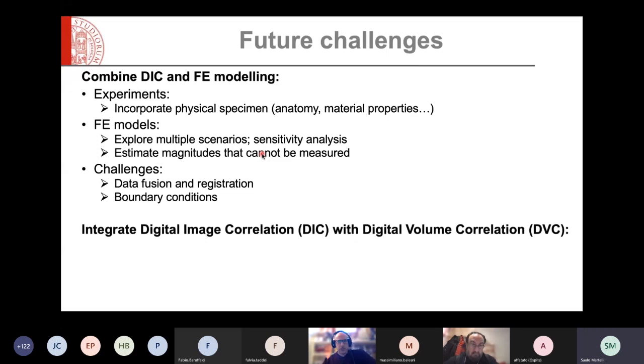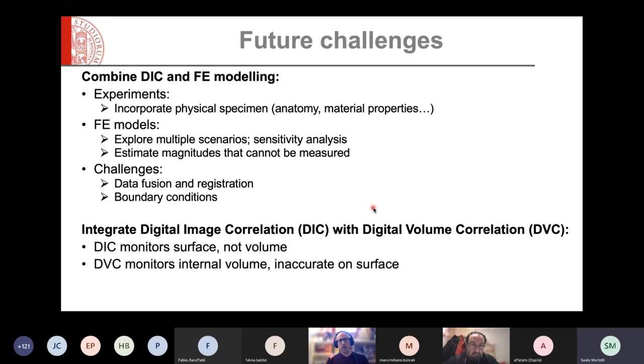Another exciting challenge is to combine surface analysis with a volume correlation so as to combine the optimal measurement on the surface from the DIC and the accurate measurements from DVC, which can only work properly on the inside of the structure. And again, the main challenges are registering the 2 systems.